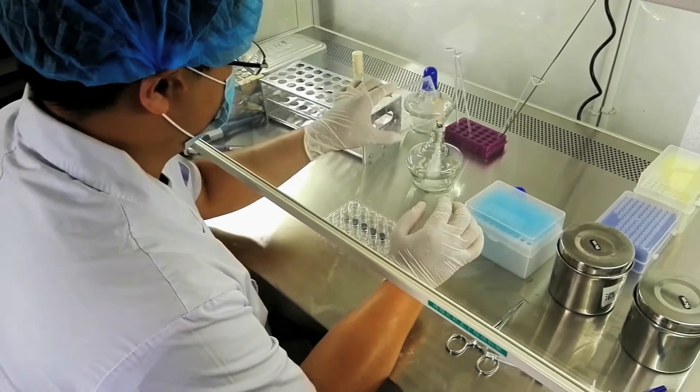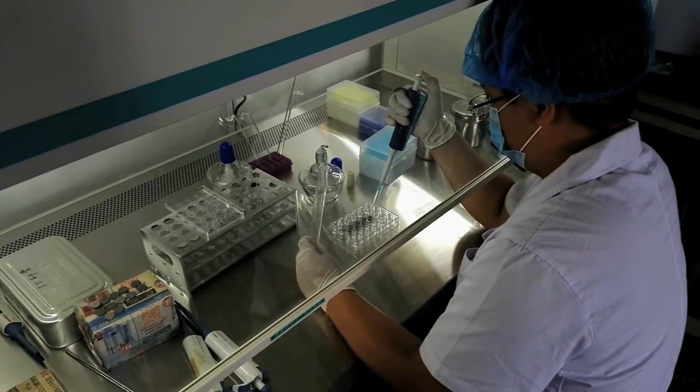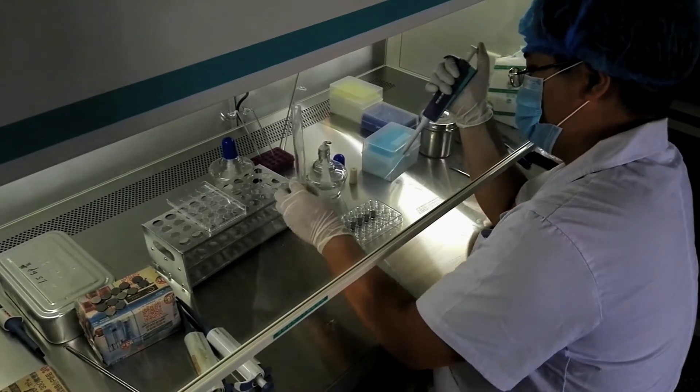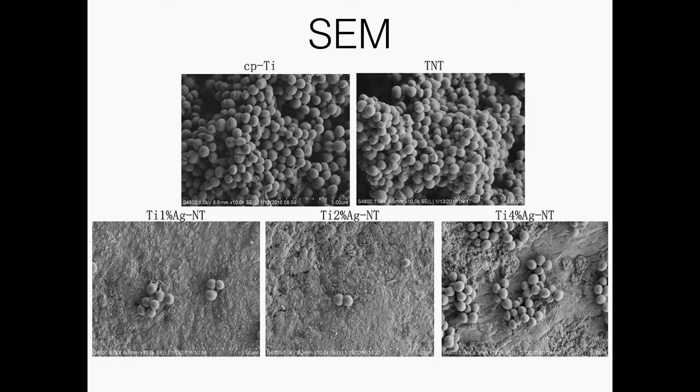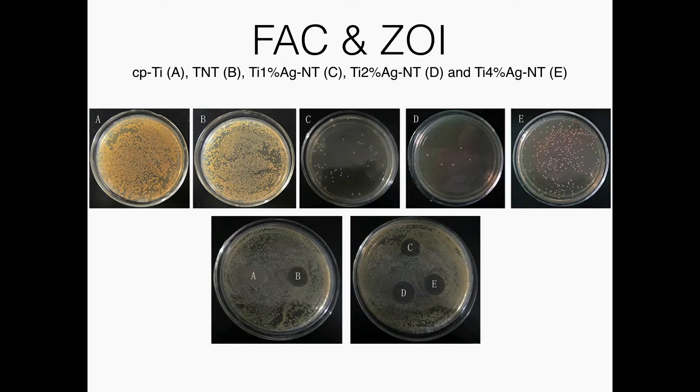The antibacterial experiments were all carried out in the Microbiology Department of China Medical University. The results proved that all of the nanotube coated titanium silver alloys, particularly the sample with 2% silver, showed strong antibacterial ability on the first day of culture. Additionally, the excellent antibacterial abilities exhibited by the nanotube coated titanium silver alloys were sustained for at least 30 days.